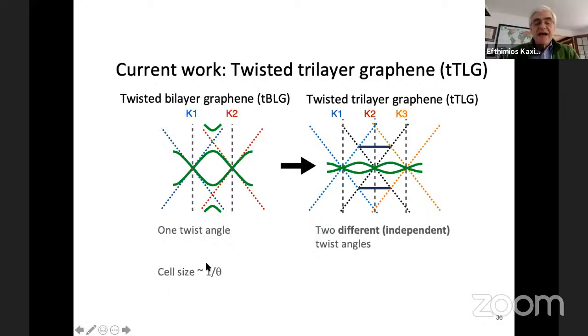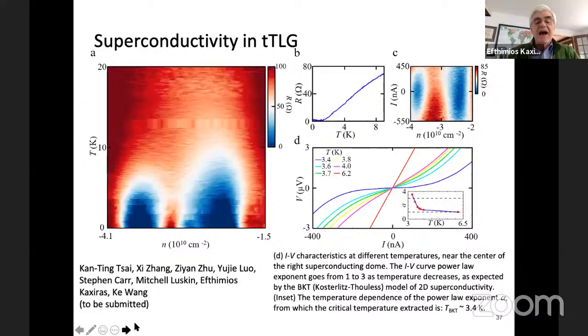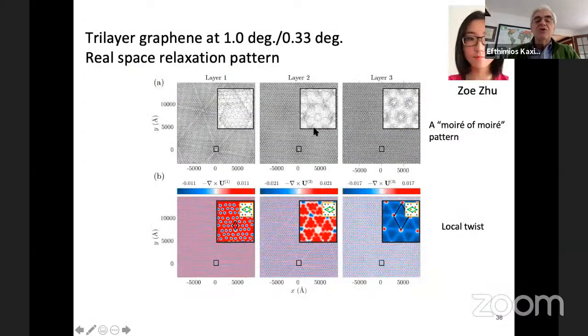And the cell size here scales as one over the angle. The angle being small, the cell size is big. In this case, the cell size scales like one over the angle squared. The angle being small, the cell size is much larger in this case. And indeed, this is the kind of relaxation that we see here. So let me just show you this first.